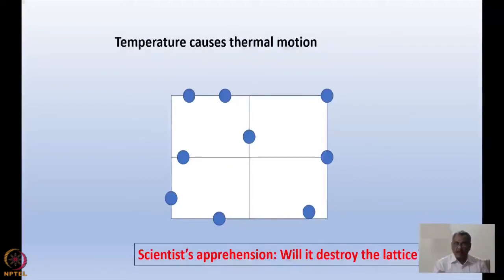But at any particular temperature, because of thermal motion, the atoms will move. If I look at any instant of time, it might look something like this. The structural experiment is basically an average of such instantaneous pictures, either over time and also over the entire ensemble of atoms or the whole crystal.